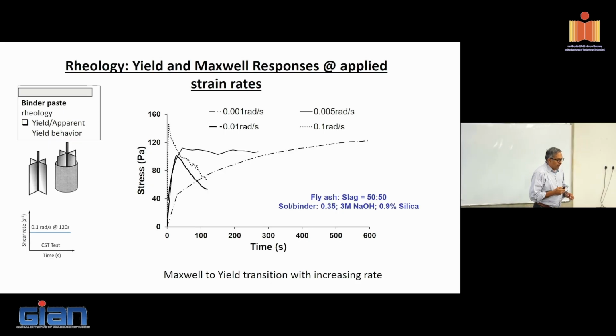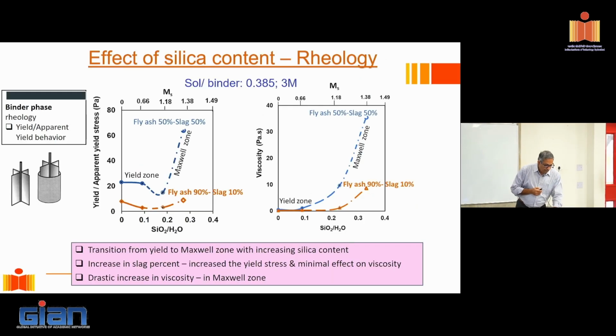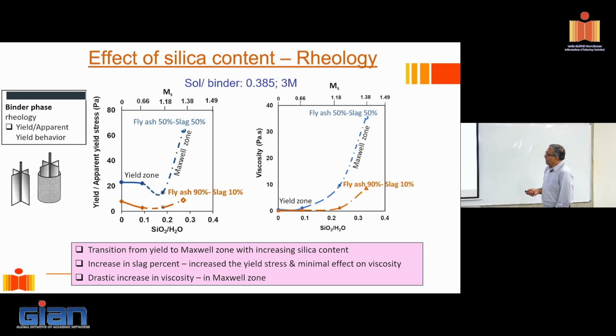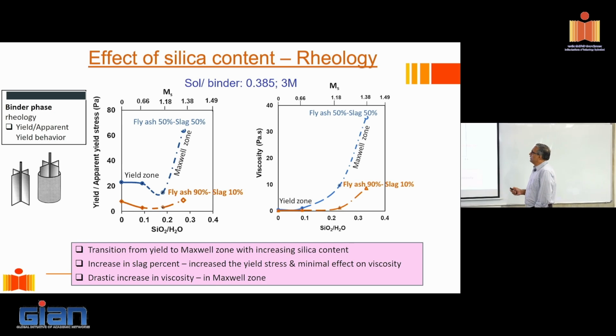Okay. Now, other interesting things start to happen. Suppose I look at an alkali activated paste with a solution to binder ratio of 0.385 and I increase the silica content in there. I'm basically keeping the solution to binder ratio constant. It's like keeping the water to cement ratio constant, changing the composition of the water or the activating solution. And how am I changing it? By increasing the silica content. Okay. Look what happens here.